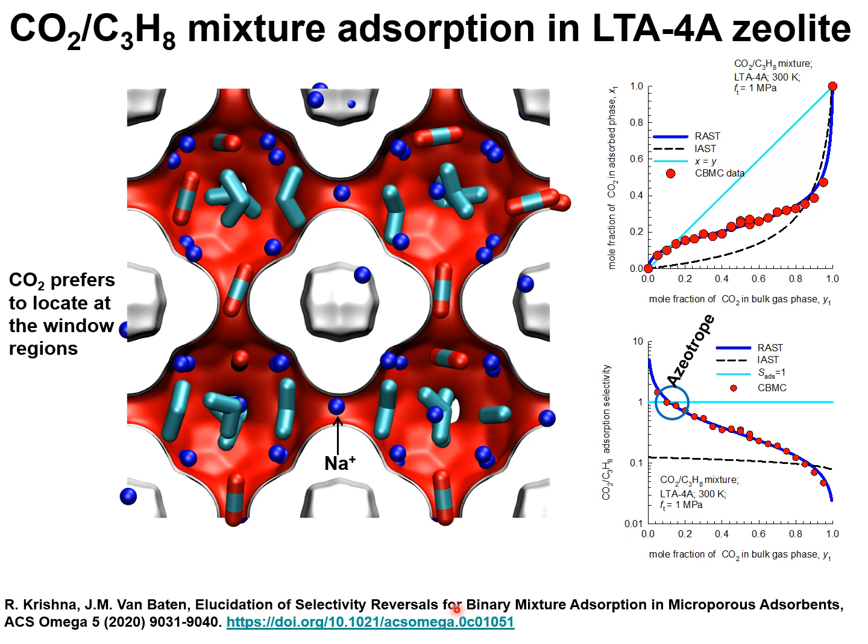The selectivity reversals are predominantly or primarily caused due to inhomogeneous distribution of adsorbates within the pore landscape. Indeed, the deviation from the IAST is the reason for azeotrope formation and selectivity reversals.